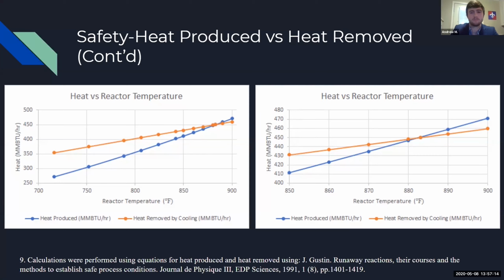And then on the right, it's a little zoomed in, and once the heat produced passes the heat removed, that's when you have the potential for a runaway reaction. And that temperature is 883 degrees. So anything after that, you would need more flow rate of quenched hydrogen into the system to cool it down and prevent a runaway reaction.